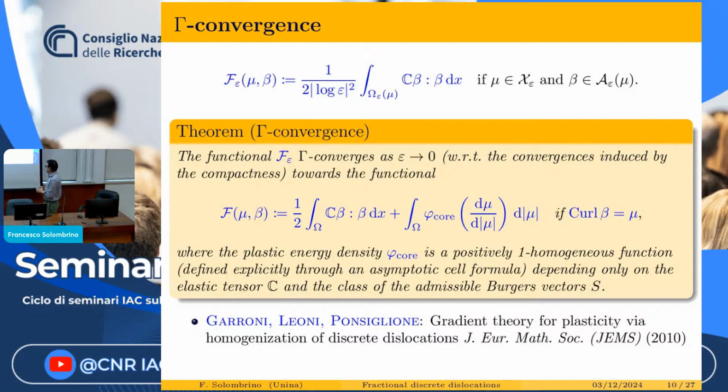Since then there has been a lot of contributions: extensions to nonlinear settings, different scalings of the energy, renormalized energy when one dislocation interacts with the others, but this was the starting point of a research program. On the other hand, this was heavily based on the fact that this core-radius approach was used, and there were some attempts to remove this assumption. And we thought of a possibility based on a different modeling in elasticity, which is no more using the traditional strain gradients, but instead based on non-local interaction between elastic bonds.